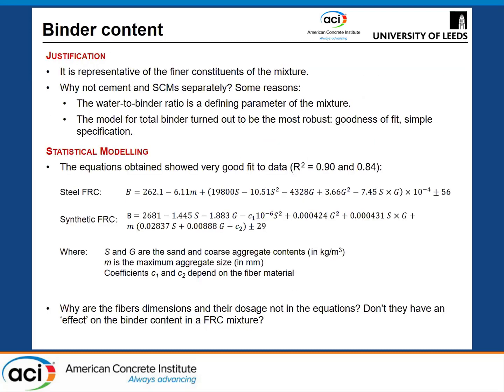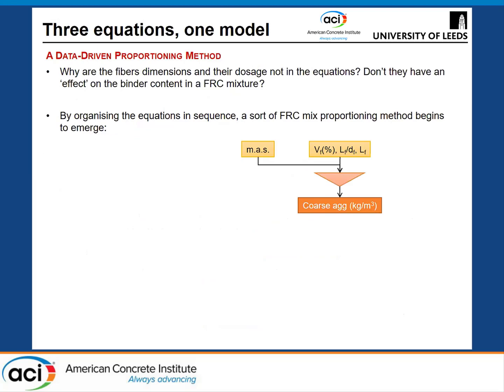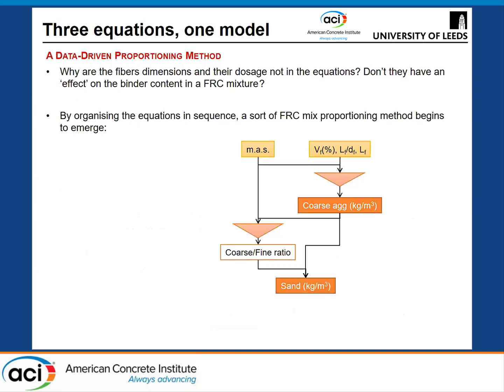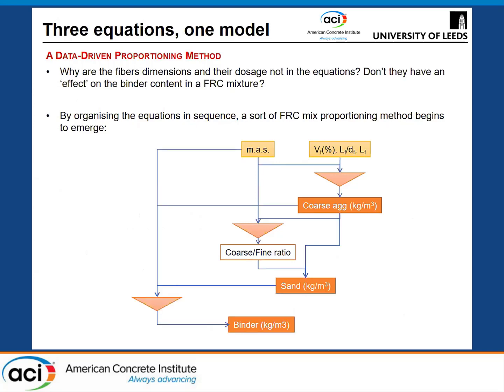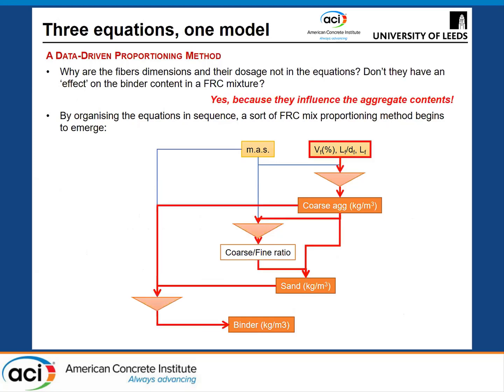But then in terms of the binder content, it was also interesting to see that the fibers were not in the equations explicitly, but the binder content was a function of the coarse aggregate content. So in a way, when we organize these three equations that I've just told you about, you have one equation which, based on the maximum aggregate size and the size and dosage of the fibers, gives you the coarse aggregate content. Then you have another equation that gives you the coarse to fine aggregate ratio. So based on those two parameters, you can directly obtain the sand content. And once you have these two, using the third equation that I presented to you, you can obtain the binder content. And you can see that the fibers affect the coarse aggregate and sand contents, which in turn affect the binder. So yes, they are influencing the aggregate contents.